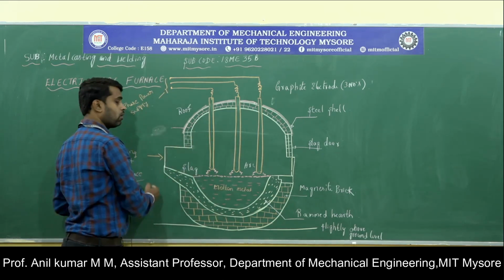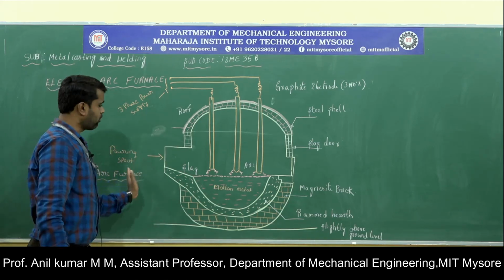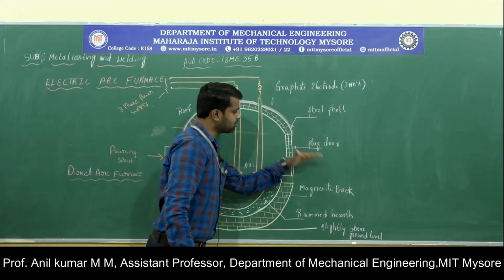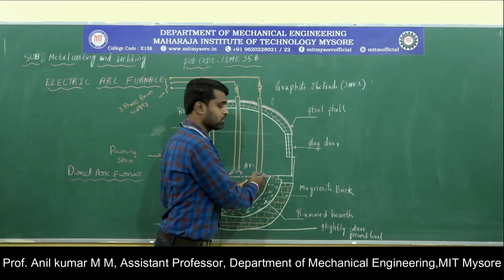Then we can tilt the furnace in the forward position and pour the molten metal into the ladle. Before tilting in the forward position, we can tilt the furnace in the backward position and remove the slag present inside the furnace.